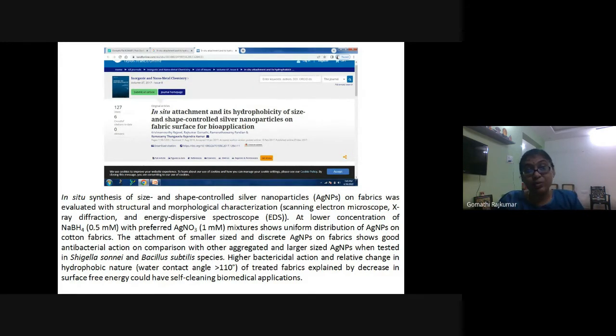Slowly, we confirmed that all the nanoparticles synthesized using the in situ method were different in size and different in shape, based on scanning electron microscopy, X-ray diffraction studies, and energy dispersive spectroscopy. So number one, it is confirmed that all these are different. Now number two, when we checked for antibacterial activity, we cut the fabric into small pieces, kept them on the plate, and checked for the zone of inhibition.